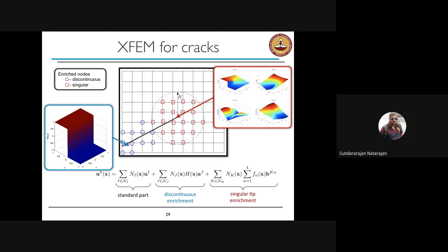Now, if we have, let's say, a hole or an inclusion in the problem, we can add additional enrichment functions that will carry the necessary information. To represent the jump behind the crack face, all we have to do is add what is called a Heaviside function. The function itself is discontinuous and the derivative does not exist, so you can capture the jump. The functions that we use to represent the singularity come from analytical expansions. For example, there are Williams expansions and other techniques which we can use as enrichment functions. And sometimes if analytical solutions are not available, what we can do is run one overkill finite element analysis and then use that solution as an enrichment function for subsequent analysis. This greatly saves computational effort.